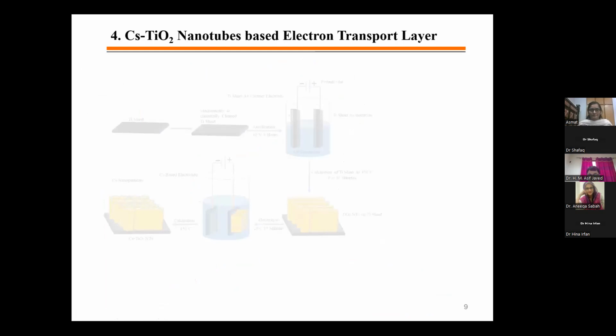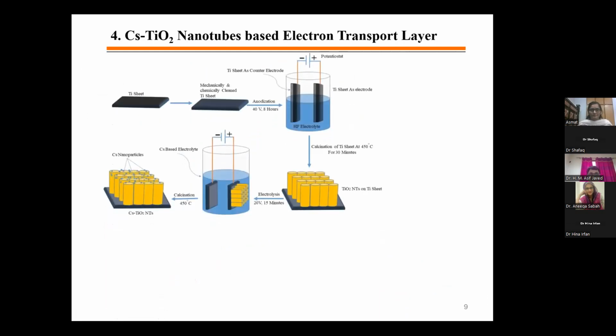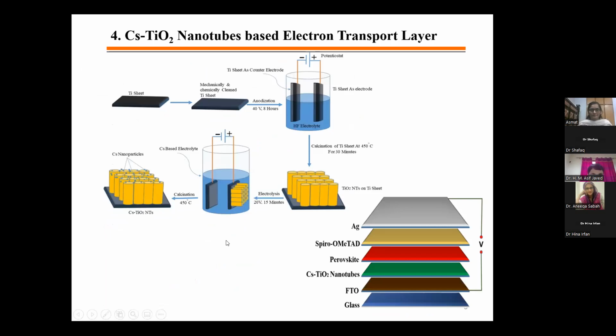We have fabricated the titanium nanotubes by the electrochemical anodization method. In this method, we have an HF-based electrolyte, and in this electrolyte, one is the anode and another is the cathode, and both are based on titanium foil. After optimizing the different parameters, voltage, time, and others, we can fabricate the titanium nanotubes. These nanotubes then go through another process to deposit cesium nanoparticles on them.